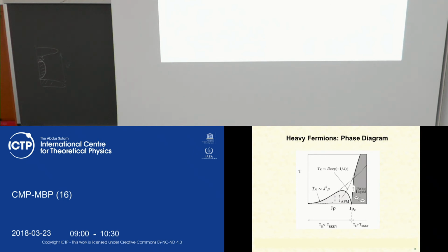D here is a bandwidth. So an exponential function is always below a power law for small values of arguments. However, at some values of arguments, an exponential function grows faster than any power law. So to say, this phase diagram, known as the Doniach phase diagram, tells that for small doping, if the Kondo temperature is much smaller than RKKY, the ground state of the system is magnetic. However, for large doping, it's a situation of the Kondo singlet, screened state. In the middle, the spin-liquid correlations develop, and these spin-liquid correlations are responsible for formation of the big effective mass and explain the heavy fermion compounds.